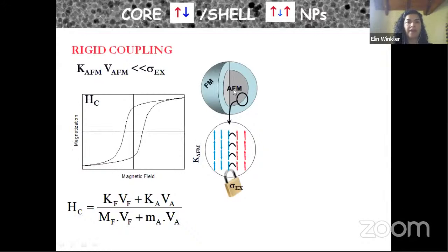In the case that we fabricate a core shell nanoparticle combining a ferromagnetic material with an antiferromagnetic one, if we look in detail at the interface, we could see that both phases are coupled at the interface. So if we now want to invert the magnetic moment of the nanoparticle, we have to apply a larger field to invert the magnetic moment, because the antiferromagnetic material has a larger anisotropy. So the coercivity field will grow, and the value will be a proportional relation between the parameters of both components.